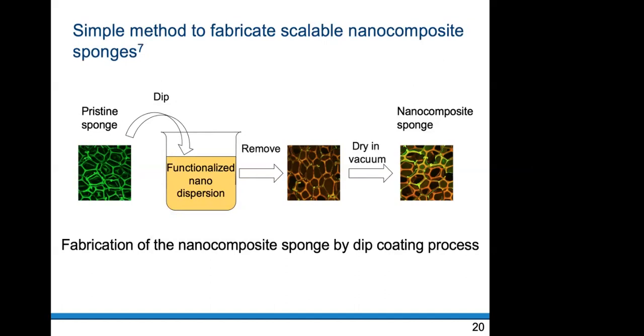So when it comes to scalability, the manufacturing process needs to be very simple. So here we developed this simple two-step process where we have this commercial sponge which can be dipped into this functionalized nano suspension. This can also be obtained commercially, or we can make it in-house. We just dip the sponge inside this suspension, remove it, and vacuum dry it or bake it to make sure this nano coating is strongly adhered to the surface. And that's all. And we can use it as much as possible.